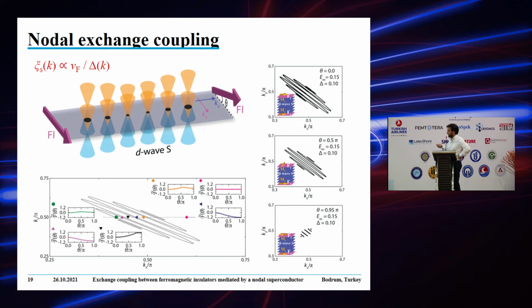So it's Dirac-like. The two exchange fields at the two interfaces basically energy-split this Dirac-like quasi-particle excitation, and they generate some pockets of quasi-particles at the Fermi surface. So this is the Brillouin zone.